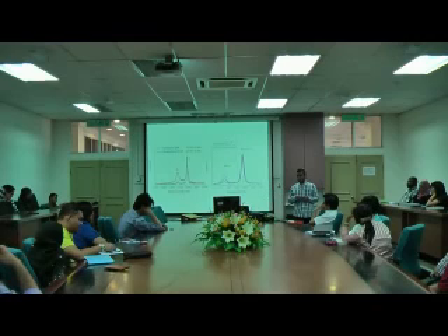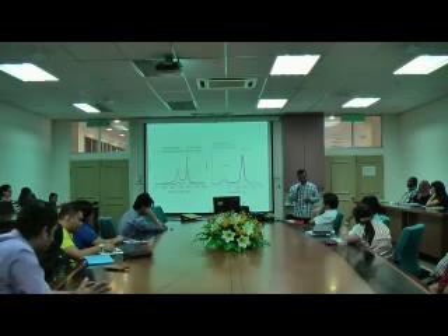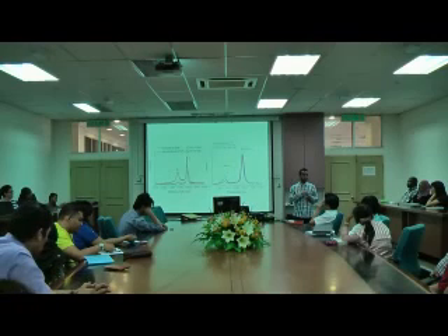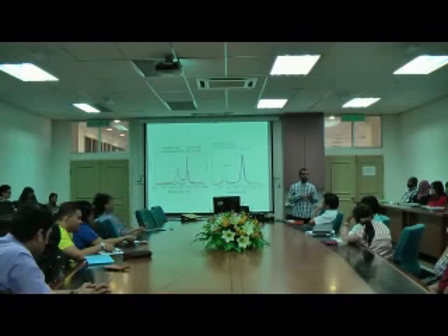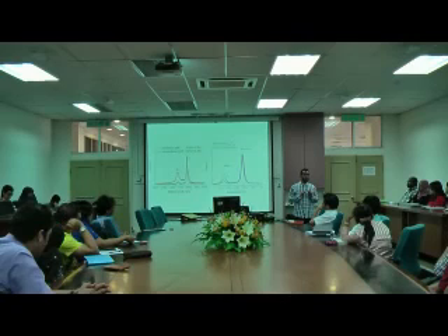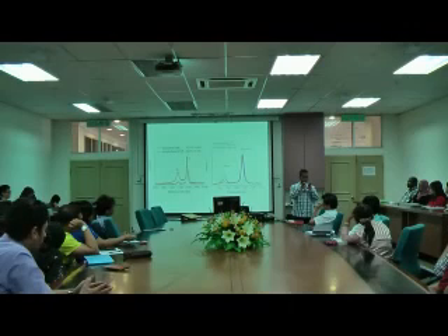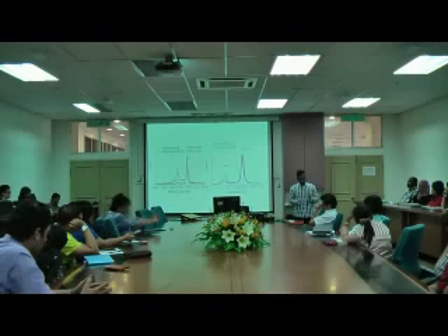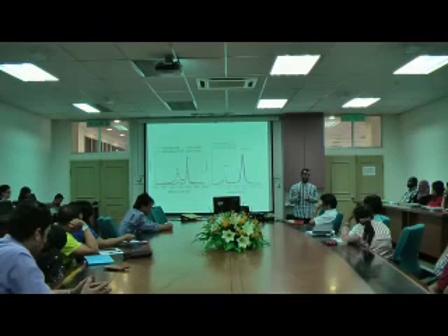Now, I believe that the different particle sizes contribute to the length of the nanofiber, the CNF that is growing. But regardless of the length, the trend is the same: they have disoriented structures, graphene arrangement. So it's not a nanotube, with stacks perpendicular to the axis, or normal to the axis. It is just growing randomly. Right. Hope that answers it.